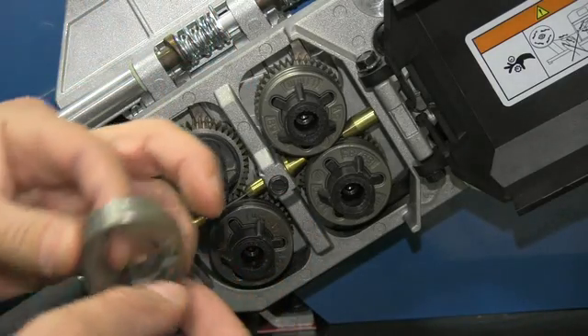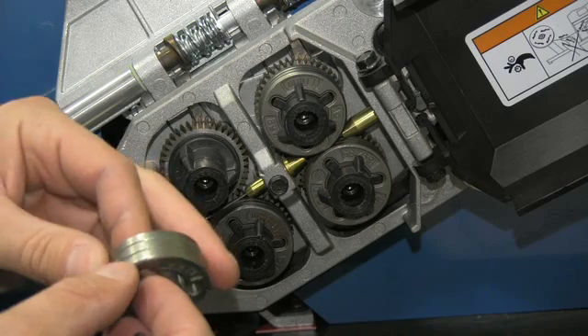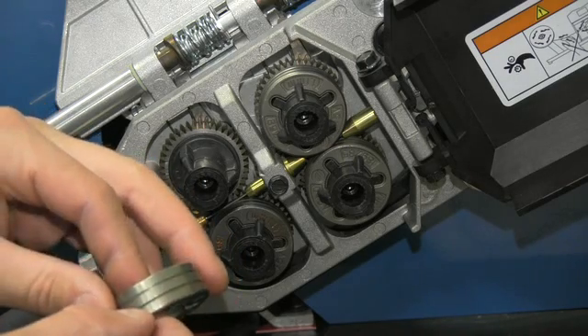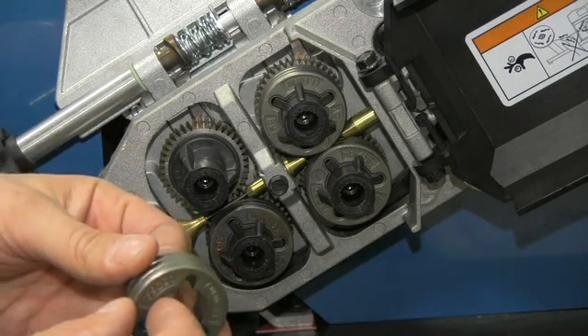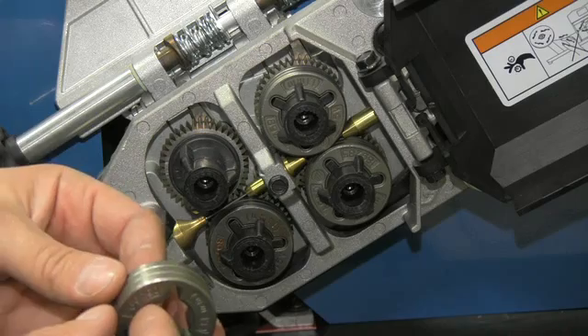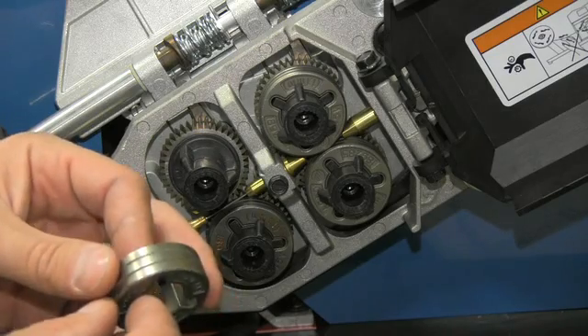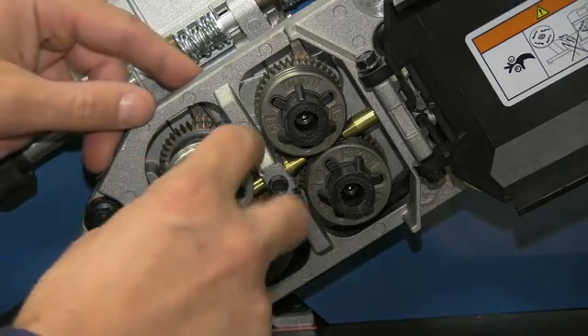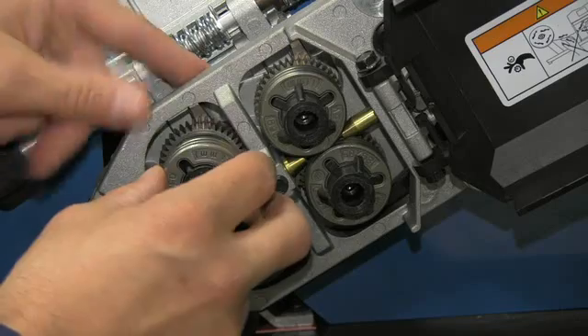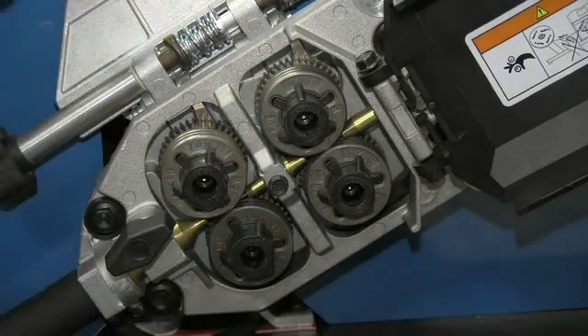You can always brush them off with a wire brush or just replace them if they get worn and there's a bunch of grease in there, because that grease will contaminate the wire and can cause some arc instability and spatter from that, and also just cause some slippage on the drive rolls. So just be sure you have some drive rolls that are in good shape. It's a real simple thing to check and it doesn't take very long.